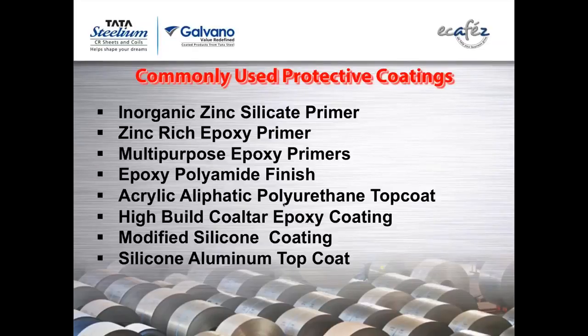Now, what are the commonly used protective coatings in the market? One is inorganic zinc silicate primer. Now, this is not very easy to apply. This is a moisture cure type. So, if you are in a very dry place, say in Rajasthan or some place like that in the summers, that primer may take 4 days to dry and still would not cure 100%.